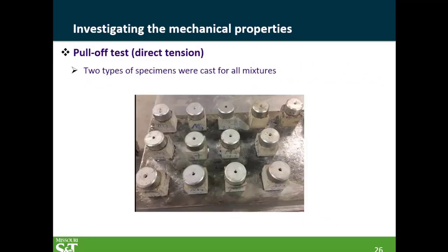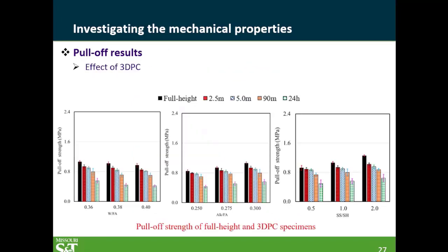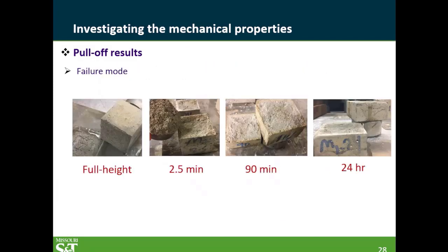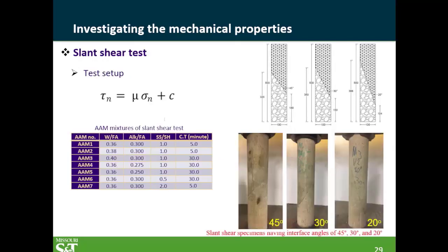And then we also did pull-off testing. So we have the different layers, and then we just did a pull-off testing to determine the tensile capacity between the layers. And these are the different failure modes that we achieve. As I mentioned, we went to some extremes just to see the full spectrum. So sometimes, if you have a really very long time, you just get what is a cold joint, if you like, and then you get the separation here.